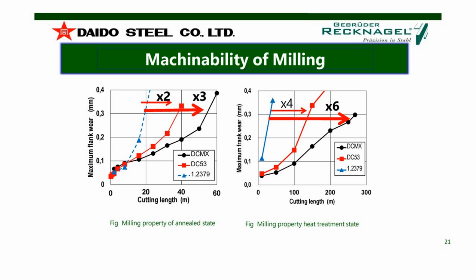This chart shows us the machining properties in the annealed condition on the left side, and on the right side we have the milling properties in heat-treated condition. And as we can see, the machinability of DCMX compared to D2 grade is in annealed condition 3 times better, and in the hardened condition it's 6 times better than with D2 grade. The measurement was about the cutting length, and I guess it's very impressive to see that the machinability of DCMX is so much better than with D2 grade.